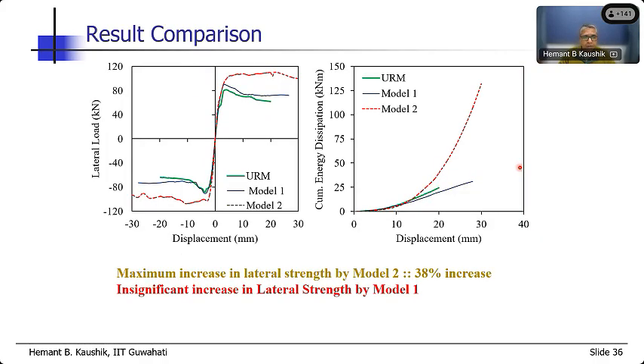And we'll compare the envelope curves. So this is unreinforced masonry, the scheme 1, marginal increase in the strength, but significant increase in the deformability that we have seen. But when we use the scheme 2, you can see there's a significant increase, about 30% increase in the strength and about, I think, 50% increase in the deformability. So that shows how effective these very simple strengthening schemes can be in case of the unreinforced masonry building.